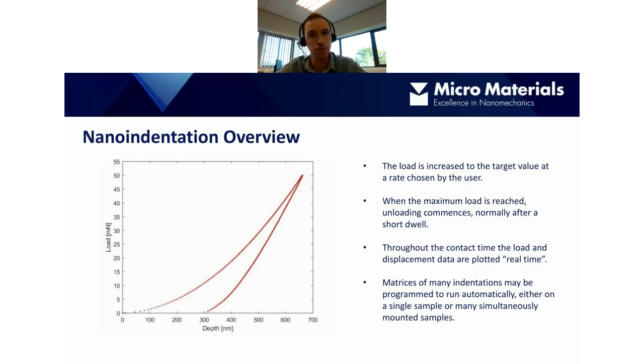After this is what we call the loading curve, and then usually after a short dwell period where we hold the maximum load constant, we have the unloading curve here. This is where the load is reduced. Again, the user can define the unloading rate until we get down to zero load. Of course, the load and the depth data are plotted in real time.